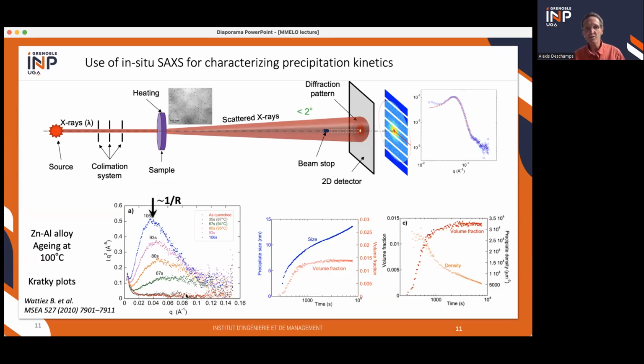And actually, you can model the full data, but more or less, in this plot, which is in reciprocal space, such as diffraction, the position of the maximum tells you the reciprocal of the size of the particles, and the area tells you more or less the volume fraction, if you know the composition of the precipitates. And so when you do that in situ, you can get a very precise estimate over time of the size, the volume fraction, and when you know the two, you can evaluate the number density.